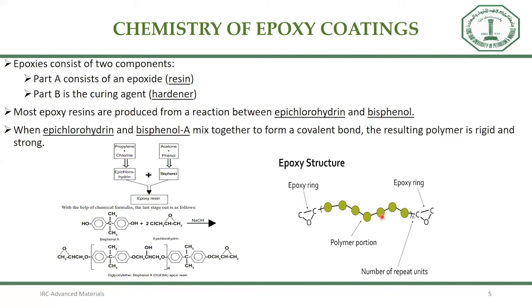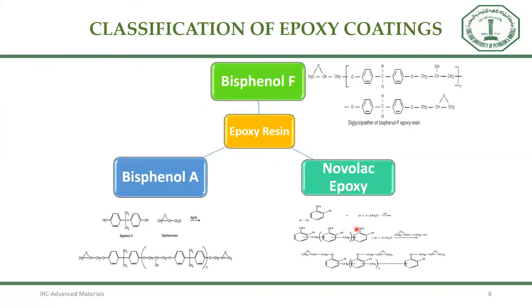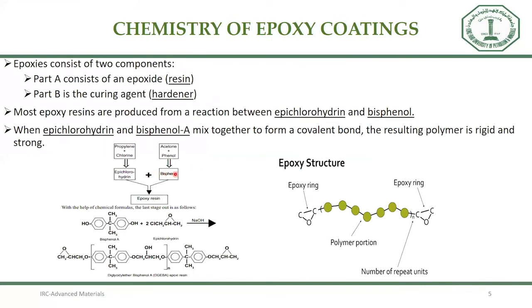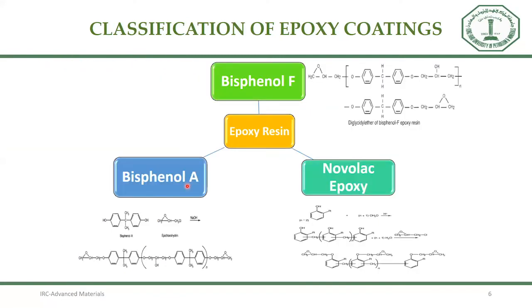When you look at the epoxy structure, at both ends it has the epoxide ring along with a number of repeating units. There are 3 different classifications of epoxy coatings based on structure: bisphenol A, F, and Novolac epoxy. Here, the A in bisphenol A refers to acetone, because it is prepared from acetone and phenol. So we call it bisphenol A. If it is prepared from formaldehyde and phenol, it is considered bisphenol F. At the same time, when we use some aromatic component here, we call it a Novolac epoxy.